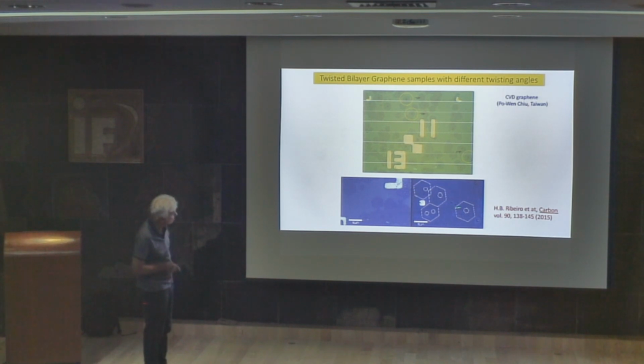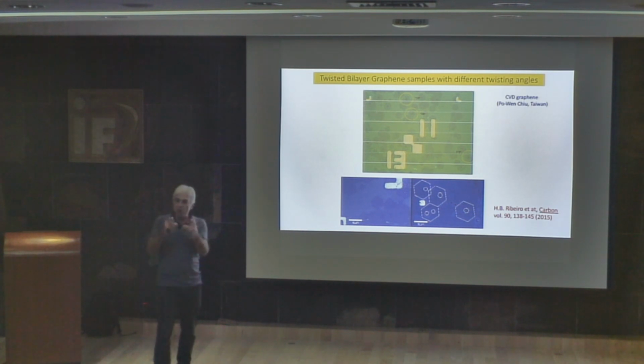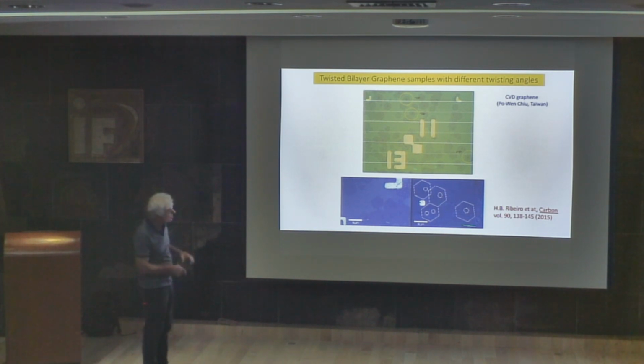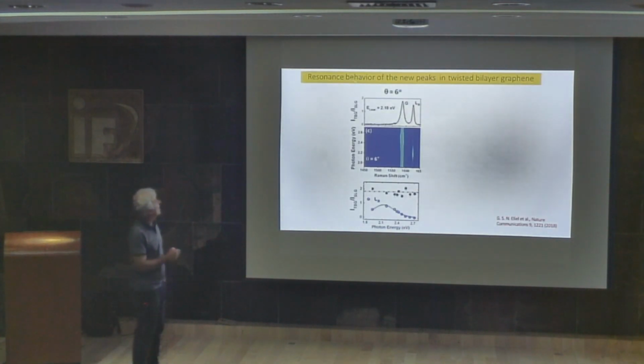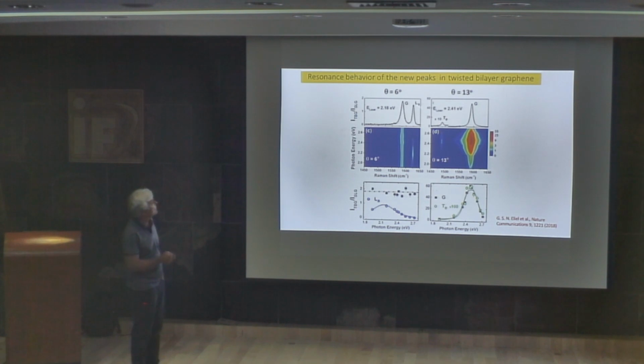For example, this is the best to see. Here is one layer. In the center we have a second layer. And since the shape of the samples is hexagonal, we can estimate the twisting angle. And after that, do Raman spectroscopy. Okay, then what I'm going to show here is one sample of 6 degrees, another sample of 13 degrees.